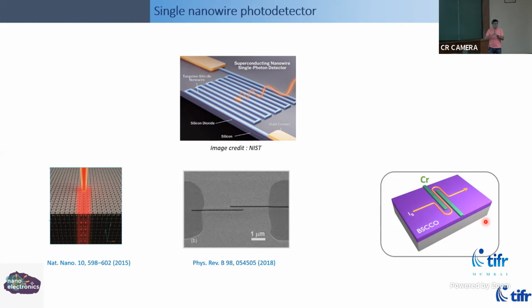sub 20 nanometer thick, we found out that if you, on the top of the superconductor, sprinkle some chromium or some titanium, it actually destroys the oxygen stoichiometry locally because these are extremely electronegative elements. So they will essentially react preferentially with oxygen, and then the material underneath is completely off stoichiometric, no longer a superconductor. So we figured out that this can be done down to very small length scales. I'll show you an example of it. So you can make these without degrading the superconductor as much as these techniques do. So you can make it quite nicely.